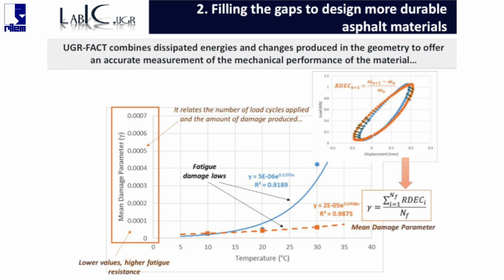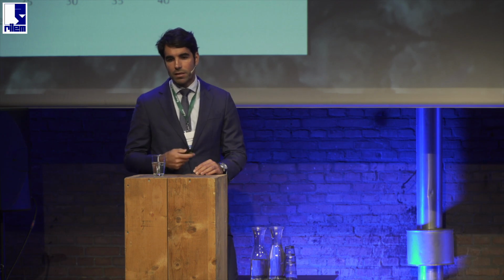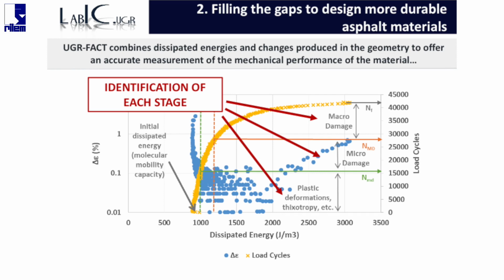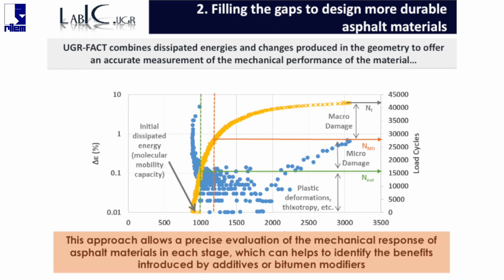And varying the temperature condition or the load condition that we are using to evaluate the material, we can obtain fatigue laws that help us to design more accurate asphalt material. So basically, with this test, we can easily identify each of the stages of the mechanical performance of the material and act to them to identify the benefits produced by additive or other bitumen modifier in each of those stages.